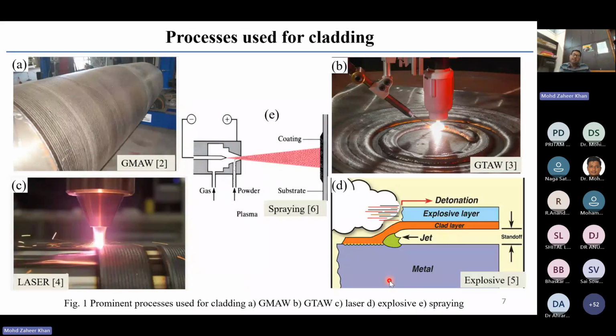This jetting action basically creates interlocking of the clad layer with the substrate material. But this process of explosive cladding requires special care because a high amount of explosive has to be burned. So there are safety concerns. If the material is not very ductile, particularly the clad material or even the substrate material, then because of the impact of the plate, cracks can develop. So this also suffers certain limitations.